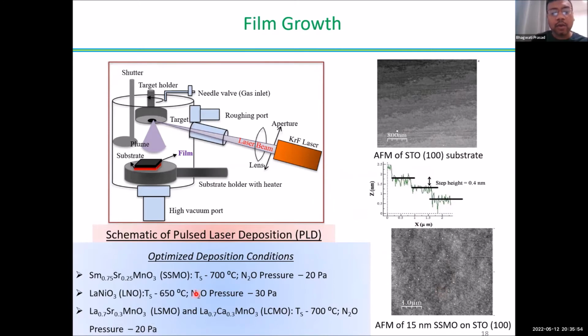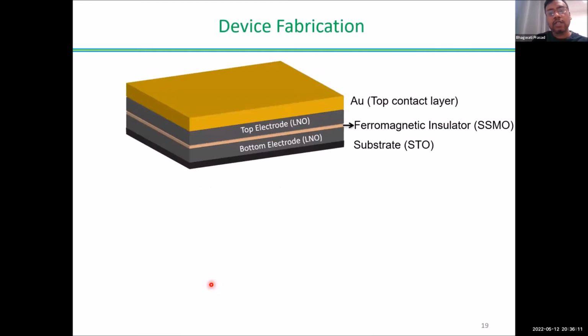Okay, so I have used lanthanum nickelate as a bottom electrode, and also lanthanum strontium manganese oxide or lanthanum calcium manganese oxide. So these are the bottom electrodes, and samarium strontium manganese oxide, SSMO, is my ferromagnetic insulating barrier layer. Okay, now let's come to the devices. Once we grow the films, we fabricate the devices. So this is the substrate, then we use the bottom and top electrode, lanthanum nickelate, and then SSMO is the ferromagnetic insulator barrier we have.